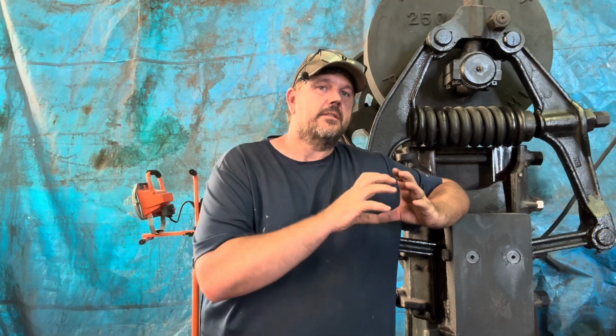So I want to talk a little bit about the grain reduction cycling process. As you forge weld steels together, especially Damascus steels, the grain tends to grow. With each high heat that you take the steel to, even with just regular forging, you will get grain growth. So you want to bring that grain back to the way it was originally in the steel before you started forge welding. So you heat it to 1525 or 1550 degrees, and let it cool down to black. Then you take it to 1400, cool to black, 1250, and cool to black. What that does is it takes those grains that have grown over the whole forging process and shrinks them back down.